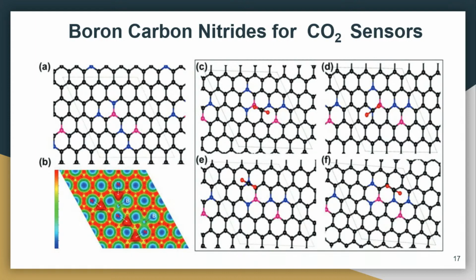And this is your density map for the BCN. Here you can see the electron deficiency in some places, which is induced by your boron substitution, and you can see in some places the electron concentration, the density is very much higher in particular places, which will be due to your nitrogen substitution. Okay, and we calculated the CO2 adsorption and NH3 ammonia adsorption in different places. So what we believe is, when you have a nitrogen substituent here, this carbon will act as an active center, right? Because it will increase your electropositivity here, so your N can be substituted here.